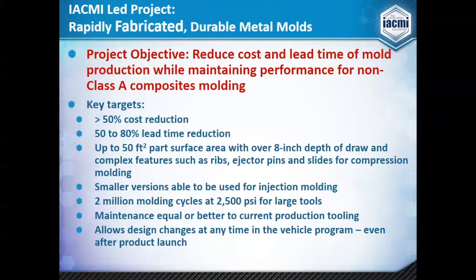We definitely want to be able to look at complex features. How do we get the ribs in? We obviously will need ejector pins, and then, can eventually build these with slides as well. Don't know, because of the pressures involved, whether we can get all the way up to the high pressures of injection molding on tools this size, but most injection molded parts are well below this size. So we believe that we'd be able to get to up to the 10,000 psi peak pressure that you might need for injection molding.